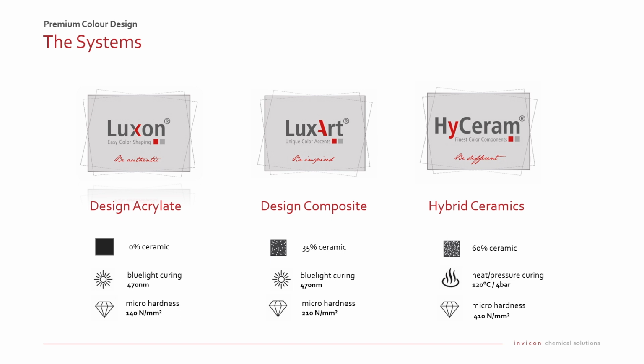And the ceramic content is also very, very important for the surface hardness. If you see, Luxon creates a surface hardness finally of 140 Newton per square millimeter. When LuxArt is involved with a 35% ceramic, the surface hardness increases already to 210 Newton per square millimeter, and it goes up to 410 Newton per square millimeter when it is related to HyCeram with a 60% ceramic. So the ceramic content is crucial for the surface hardness we achieve finally.